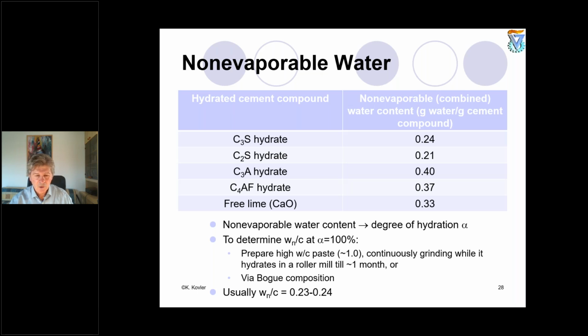We need to take care of the physics of the porosity, because if there is no room to accommodate this expansion of the newly hydrated products like CSH, the reaction will stop. And then for having the total minimum water cement ratio needed to complete the reaction of Portland cement with water, we are coming to approximately 0.4 water cement ratio, which is much higher than this chemically bound water to cement ratio.